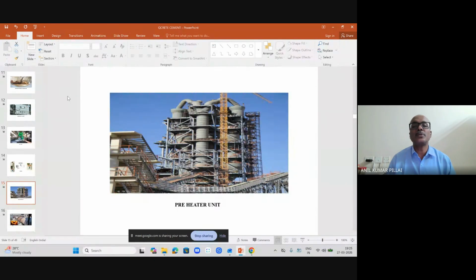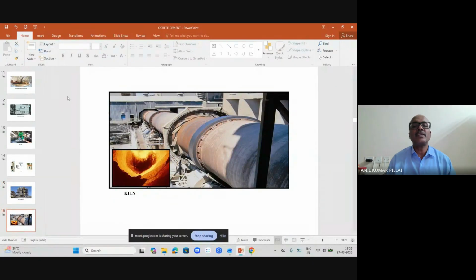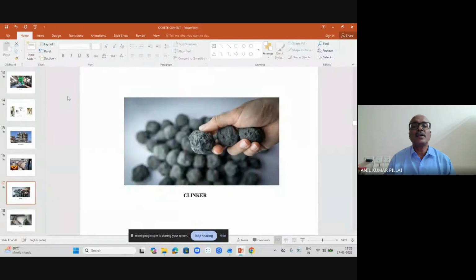Then the preheater unit is there, where it is heated to 700 to 800 degrees centigrade. The kiln, as you can see, and this is the clinker. So the properties of clinker are very important. The clinker is manufactured in such a way that the compound composition and the oxide composition are such that the properties of cement are maintained. That is how you will find that there are different types of cement.